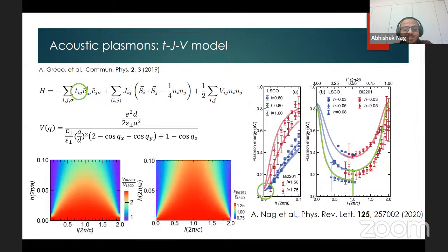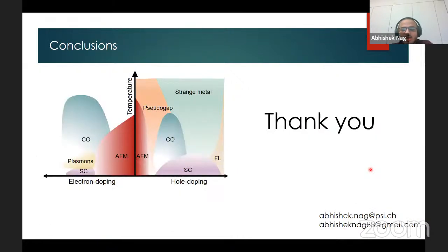So to conclude, we have demonstrated the presence of acoustic plasmons in two families of hole-doped cuprates, therefore kind of restoring the balance in the cuprate phase diagram. And these plasmons are strongly dependent on the interlayer interactions and have a strong oxygen on-site character, unlike the electron-doped cuprates, despite the strong copper-oxygen hybridization. So the perception that in-plane charge fluctuations are strongly suppressed by Coulomb interactions is not correct for these systems.